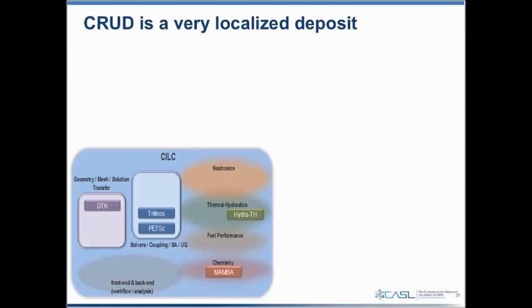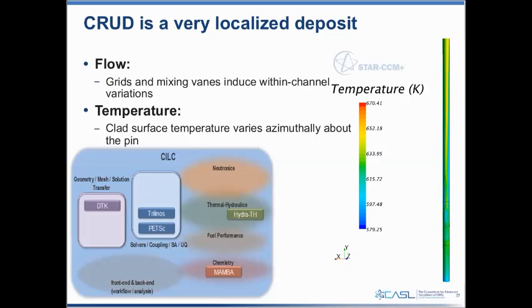So CRUD is a very localized deposit. As has been mentioned previously, this isn't something that you see in very big, large regions. To really evaluate that fine mesh resolution, we have integrated MAMBA with both Hydra-TH, as was shown earlier, and Star-CCM, so we can get CFD coupled with MAMBA results to understand that distribution on the surface of the cladding.